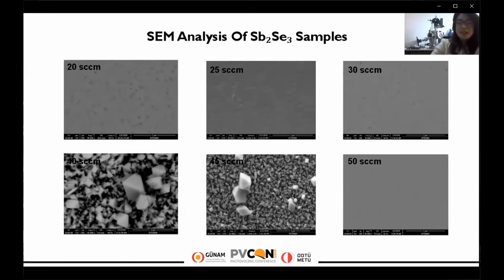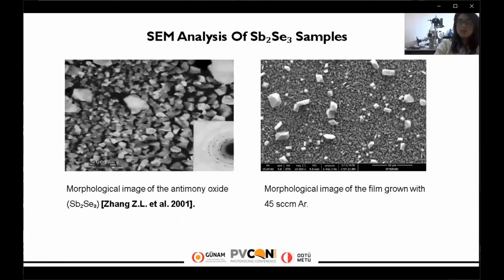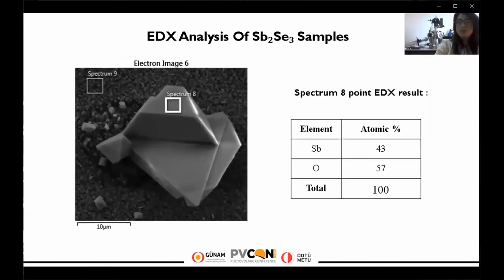It's significant. And when we look at the 40, 45 and 50 SCCM images, we see extraordinary structures showing up in these samples. It can be attributed to selenium separation from the film surface and gap formation, because at higher argon gas rates selenium separates from the sample's surface. Here, the left side picture from Zhang's article shows the morphological image of antimony oxide, and the other is our image taken from the 45 SCCM argon sample.